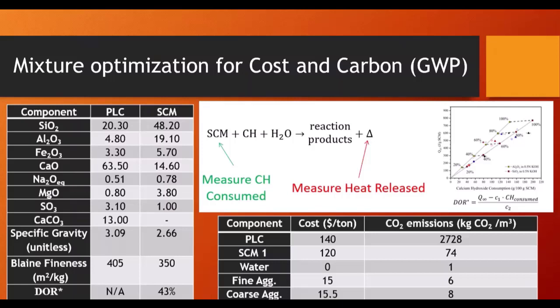And I will tell you, much like my academic career, 100% is not always the best case scenario. Sometimes getting a B in the reactivity test is really what you want to be doing because you replace more of the clinker, right? If you're at 100% reactivity, you may only use 5 or 10% of the material. If you're at 50% reactivity, you're now replacing 30% of your clinker, which drops your GWP value substantially.